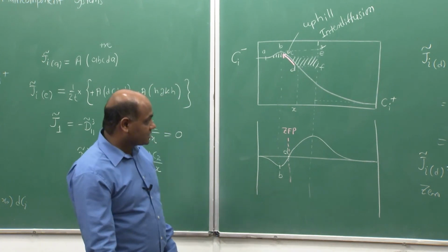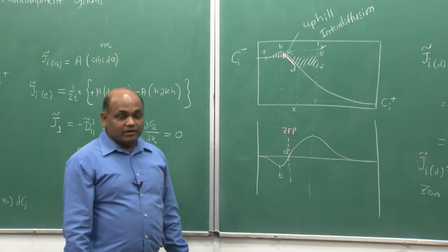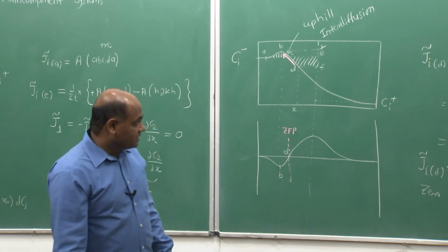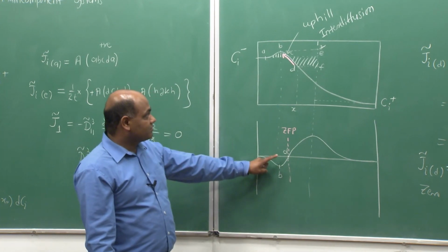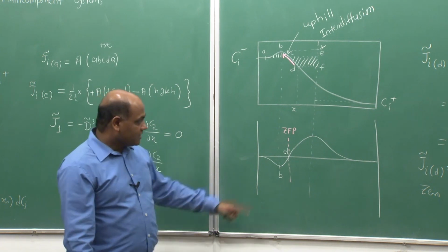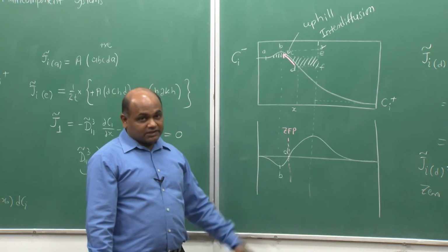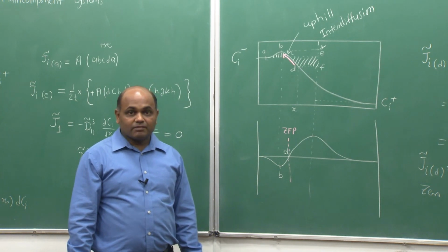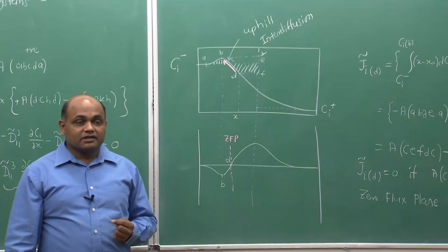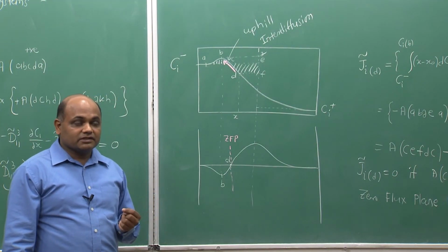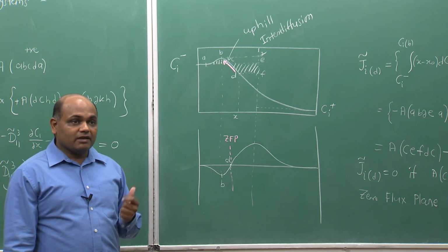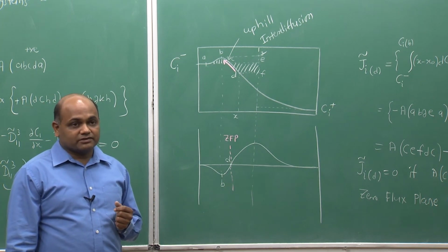These ZFPs are very important when we are studying the diffusional interactions, and we want diffusion couples which would develop ZFPs and uphill diffusion regions. Dayananda has studied such couples extensively by forming isoactivity couples. That means, a diffusion couple in which the thermodynamic activity of a component is same in both the terminal alloys to start with.